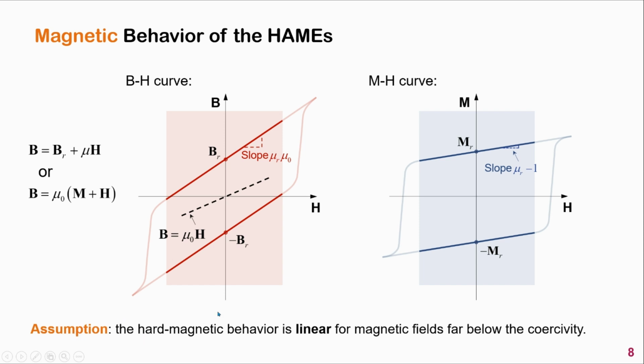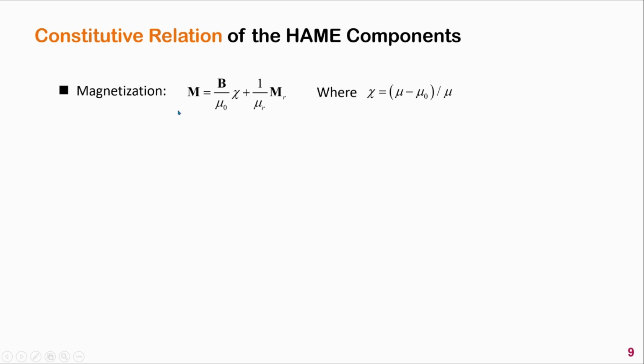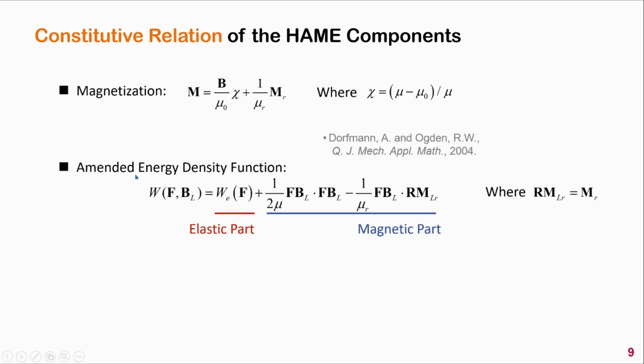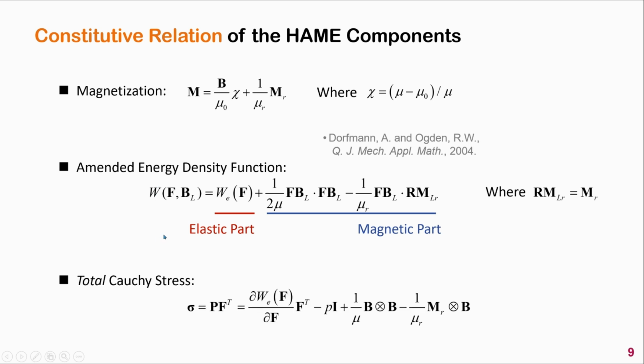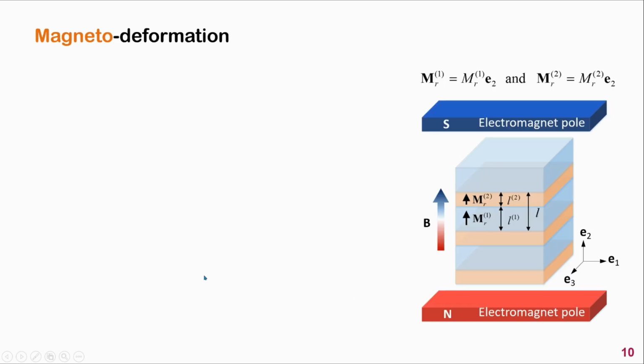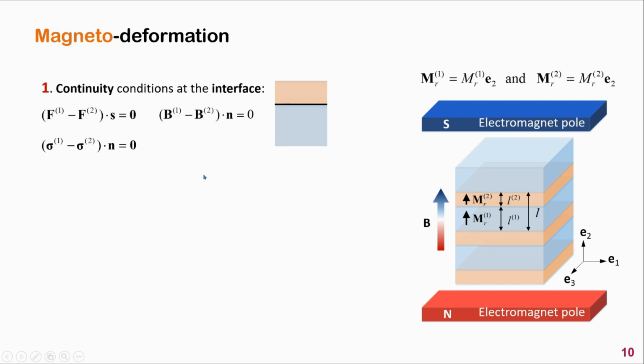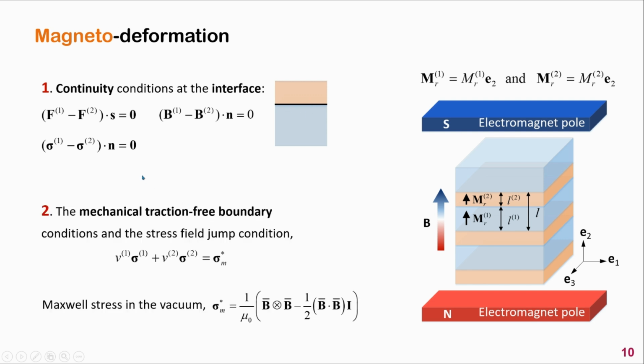With such assumption, the total magnetization can be expressed here, and the Lagrangian augmented energy density function can be written as follows. There are two terms, the magnetic part and the elastic part. Using the energy density function, we can obtain the total Cauchy stress. Now we consider the boundary conditions. First one is the continuity conditions at the interface between the layers. The second one is the mechanical traction-free boundary condition.